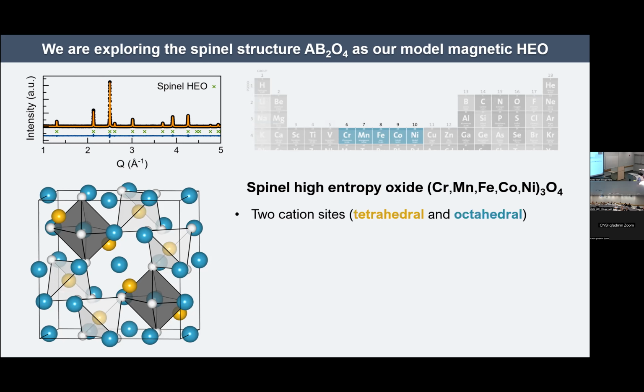And it has the cubic spinel structure. But immediately, what we can appreciate as different about the spinel structure versus the rock salt example I showed you earlier is that I no longer have a single cation sublattice. I now have both a tetrahedral and an octahedral sublattice in the material. So my yellow ions here sit at a 4-fold coordinate oxygen environment, and my blue cations sit at a 6-fold coordinate environment.